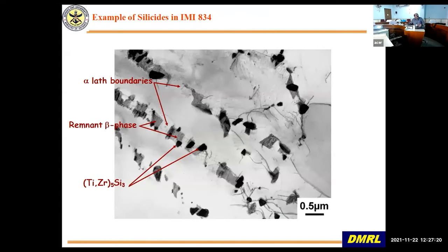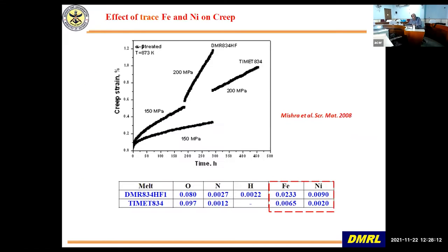Now, why do we add silicon? You can see this is a TEM picture. This is alpha lath and beta, which is this dark gray structure. This is very discontinuous. It is not a continuous lath, because the beta volume fraction is low. So when you put in silicon, it forms silicide and it precipitates around the beta boundaries and at the interfaces of alpha and beta laths. This is alpha, this is beta, discontinuous. So the slip transfer cannot take place from alpha to beta, that is, you restrict the deformation, and that is what improves the creep properties. It also prevents grain boundary sliding, which is one of the phenomena that happens during creep, and that improves the creep property. That is why in most of the high temperature titanium alloys, you will have silicon as one of the additions. It improves the high temperature creep property.